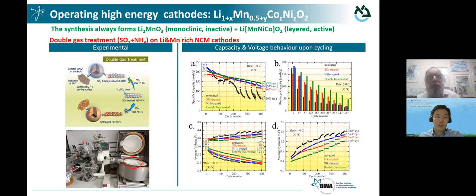And now the question is, there are many, many ways you can put coating from the solution. We can use ALD. You can put thin films. Here, I showed something very recent. We use double gas treatment. We first of all use SO2 at elevated temperature, and then ammonia at elevated temperature.